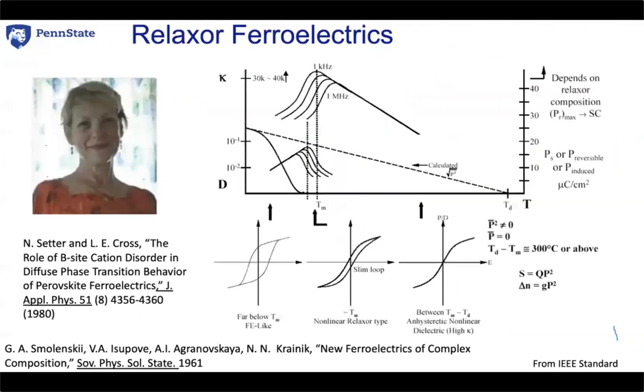Of course, key work on relaxor ferroelectrics came from Setter and Cross, where they identified that in materials like lead scandium tantalate, you could change the amount of ordering on the B-site sublattice, and in so doing, you can convert the material from a relaxor to a normal ferroelectric, and you could do this reversibly with heat treatment.